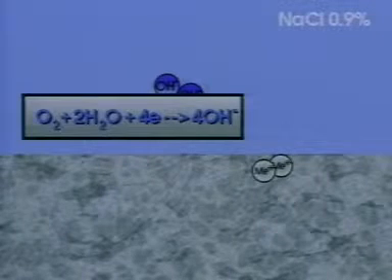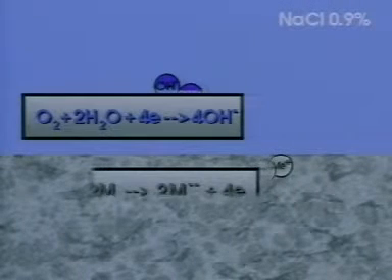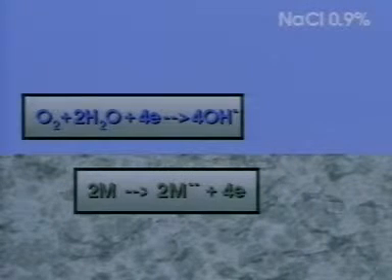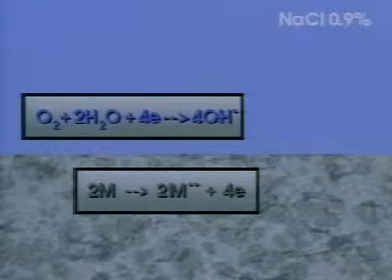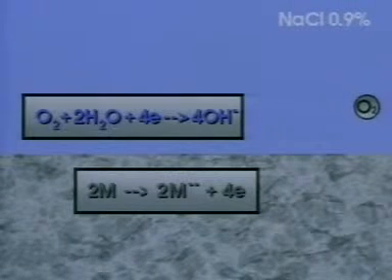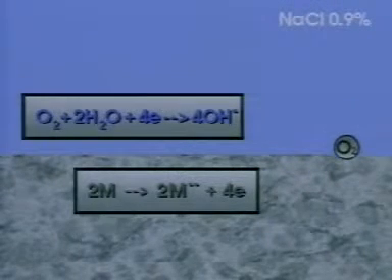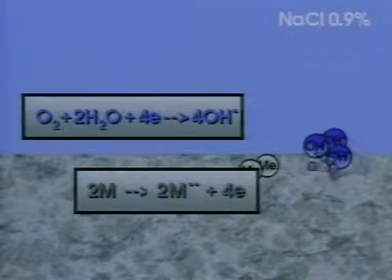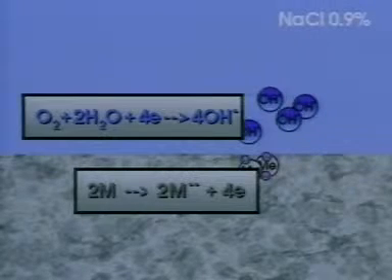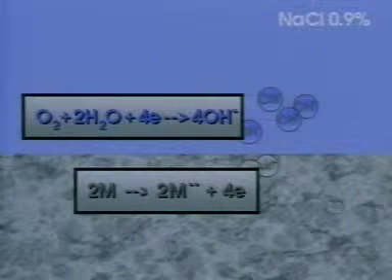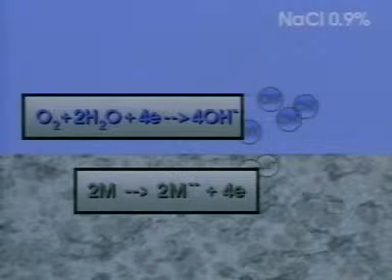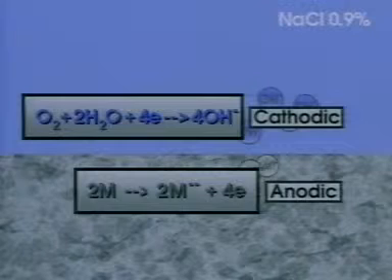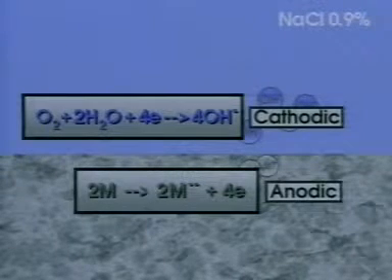An electrochemical corrosion reaction has occurred. This consists of an anodic and a cathodic partial reaction. On metals, the two partial reactions need not be physically in the same place. Electrons can be exchanged through the metal surface as an electric current. We can talk of a corrosion current which is proportional to the amount of corrosion, but we cannot measure it directly. In a corroding system, the anodes and the cathodes are short-circuited.